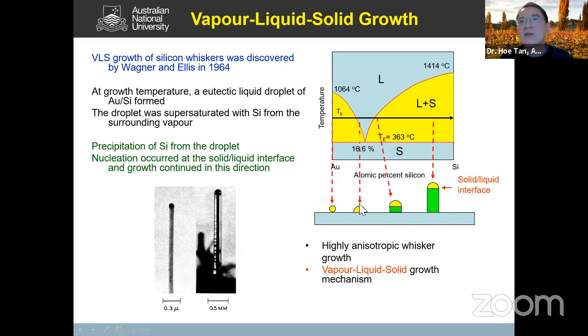Then it keeps absorbing the silicon, it keeps moving along this line until it hits this point here where it forms a liquid and solid combination. So the silicon solid will precipitate out as shown here, and continue to grow because you're continuing to pass the silicon vapor. So you end up with these silicon wires. This is the so-called vapor-liquid-solid growth mechanism, or VLS in short, because we have the vapor, we have the liquid, and then we have the solid that grows up. So this is one way of growing nanowire.